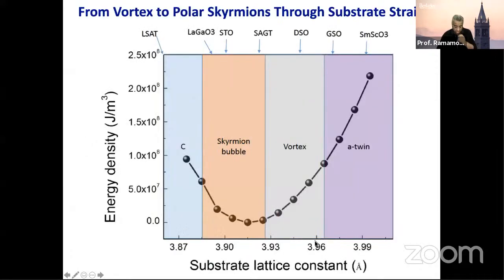Okay. Now, our theory colleagues again said, hey guys, you're sitting somewhere here. Why don't you change the lattice mismatch to the substrate that you use? For example, dysprosium scandate is what we use as our substrate for the vortices. But if you go to strontium titanate, they said you should see skyrmions. We said, guys, no chance. It turns out they were right. We were able to see them.